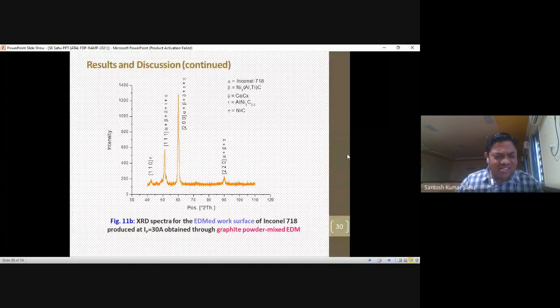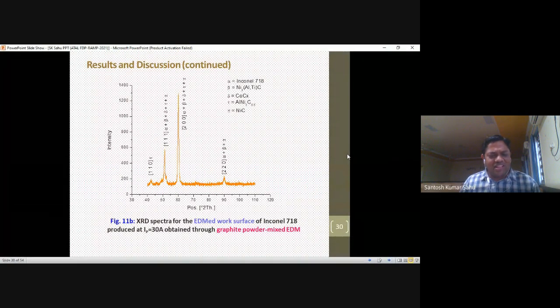While comparing the XRD spectra of the received Inconel 718 to the EDM specimen, you have to see the figure, and also when you add the graphite powder in EDM, it increases the thermal conductivity of the working medium. That's why you use this graphite powder. It is also possible due to its enlarged spark gap, which results in heat being distributed uniformly into your working zone. Moreover, multiple discharges take place for a longer period of time. This promotes grain refinement to a large extent, and the refined grain structure also relieves the thermal residual stresses.